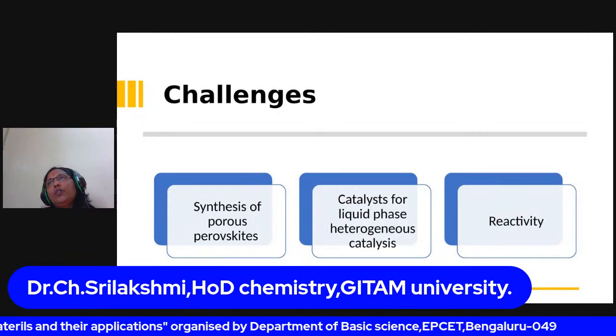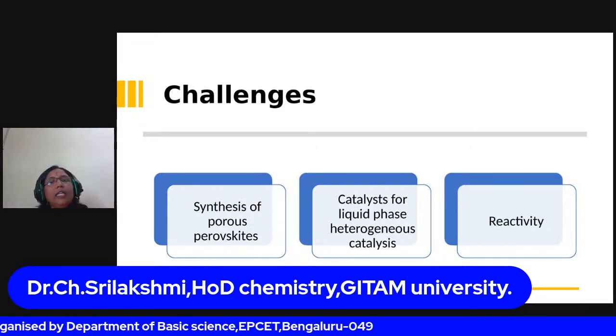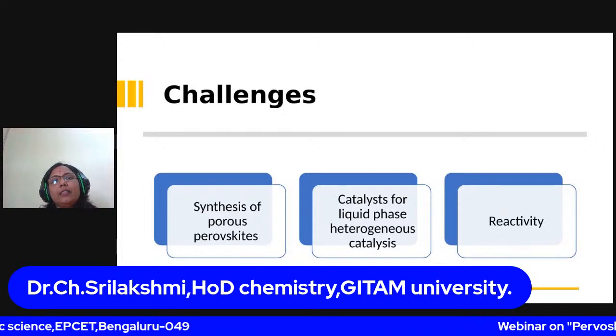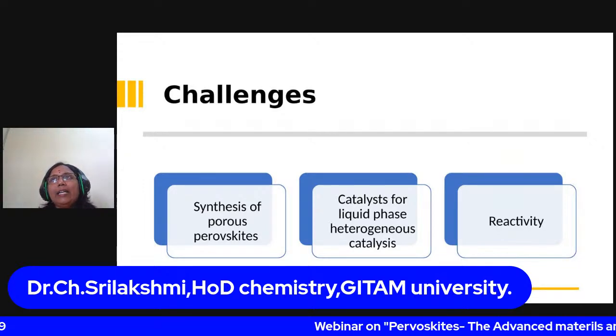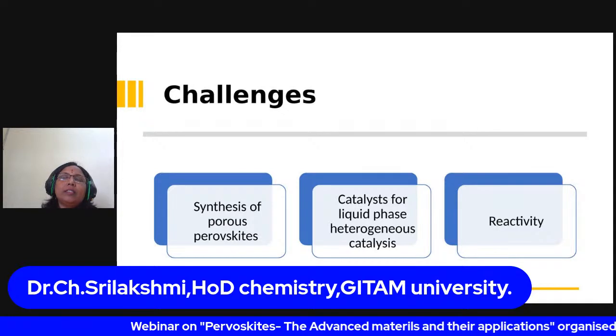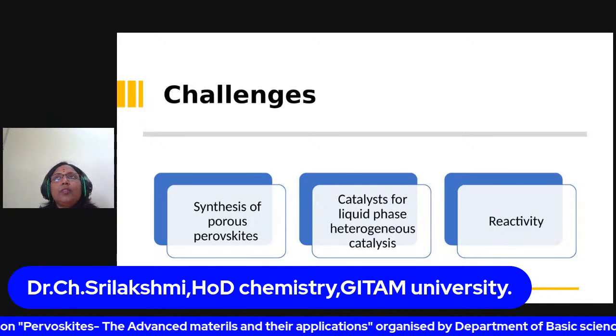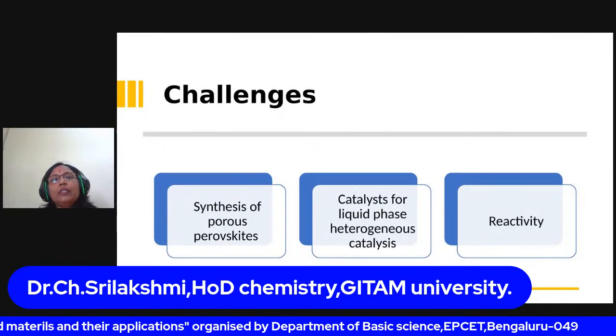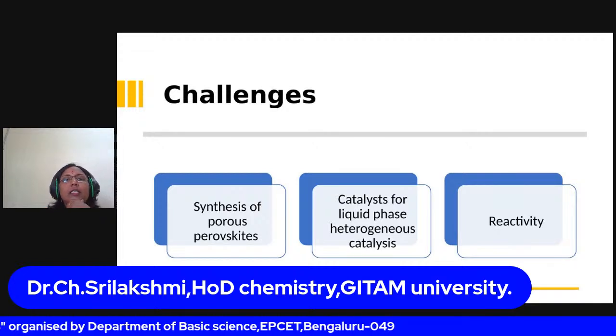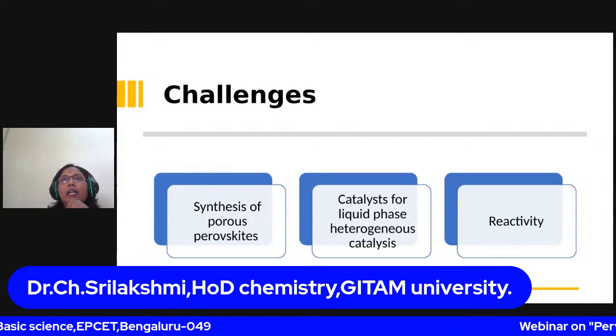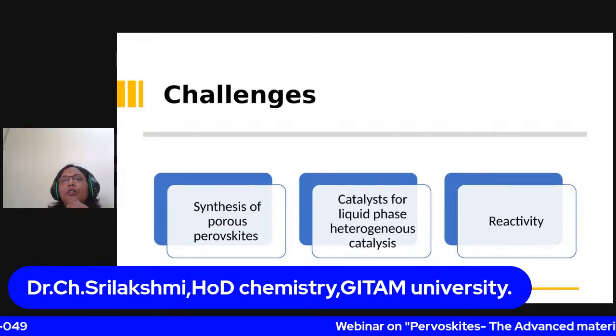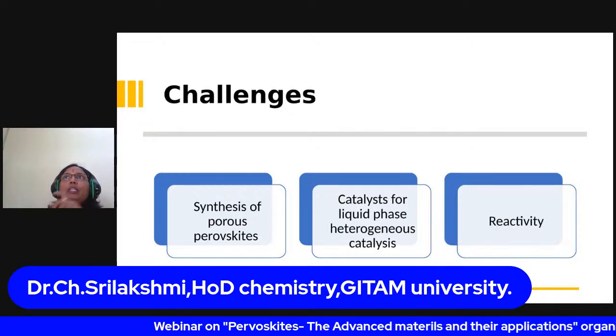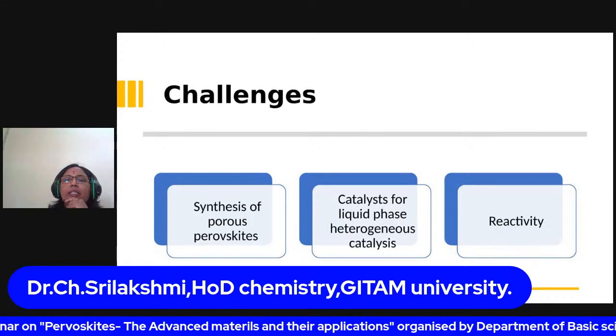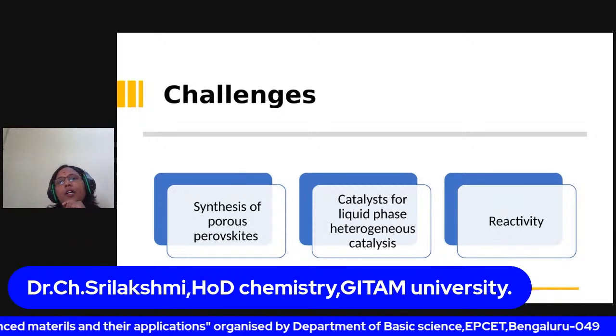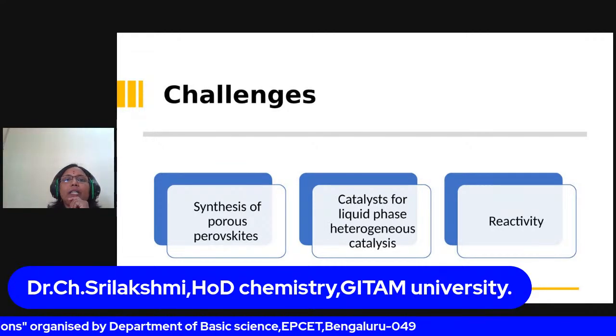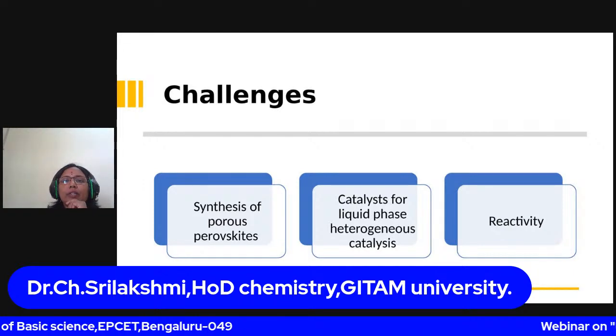So, what are the challenges in using these materials for liquid phase heterogeneous catalysis? One thing is, the catalytic properties mainly depend on the surface area of the materials. So, in order to increase the surface area, the material should be porous. One challenge is the synthesis of highly porous perovskite materials, the application of these materials for liquid phase heterogeneous catalysis reactions, and improving the reactivity of these materials for these reactions. So these are the challenges I faced during my research on these materials, mainly for applications in liquid phase heterogeneous catalysis.